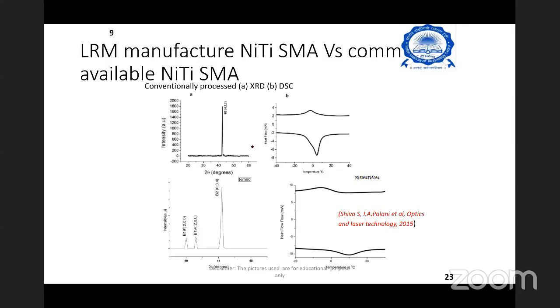So for comparison, we took the XRD and we took the DSC analysis. This is with respect to the conventionally available one, and this is the one which we have fabricated. What we could observe in the DSC is somewhat matching with the conventional available system, and whatever B2 phase is available with the conventional system, the same B2 phase we could achieve. So this is an interesting aspect with respect to laser additive manufacturing.